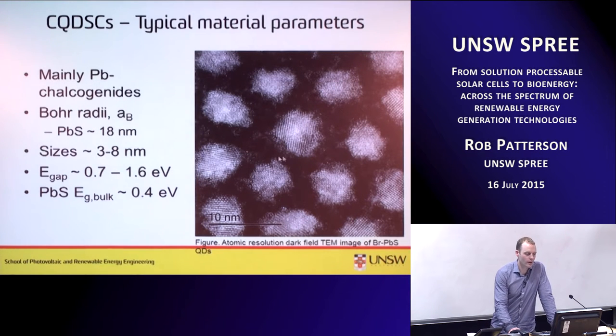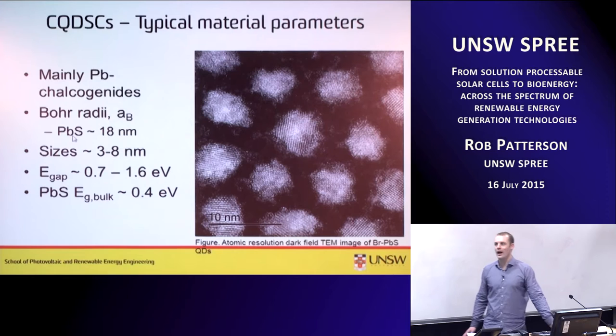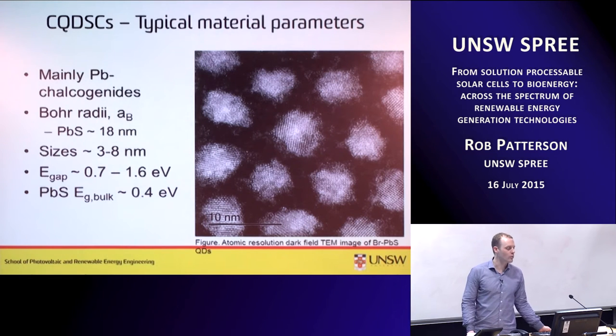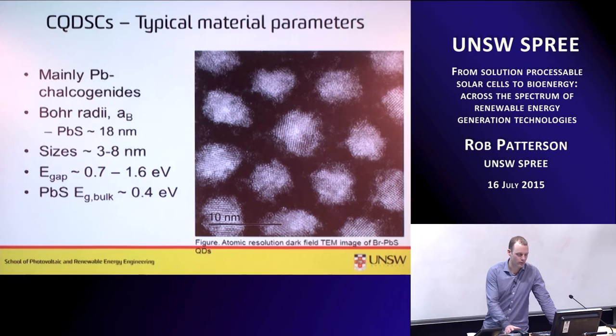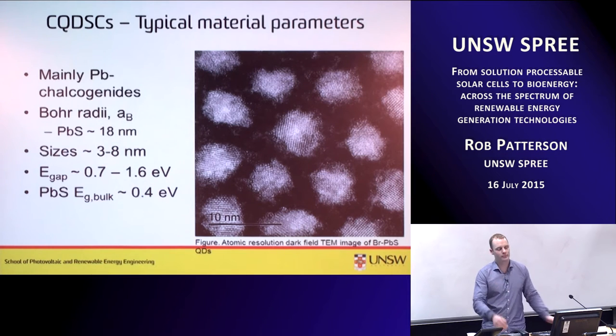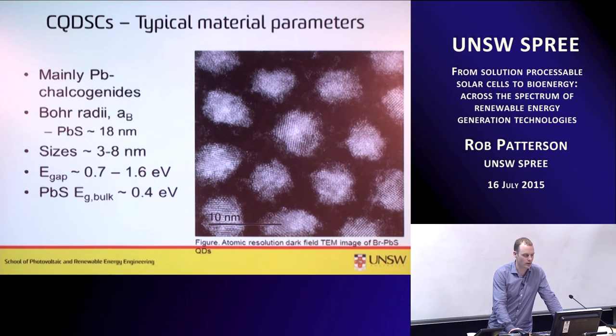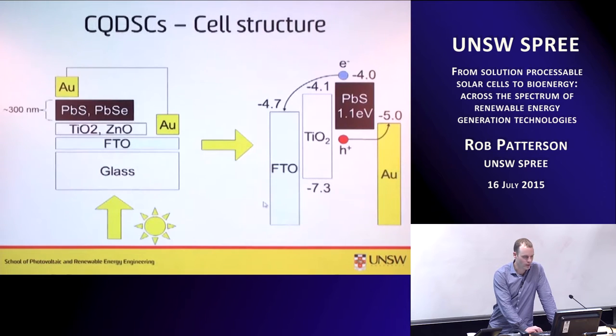So we like materials that have large atoms in them because they have potential for large Bohr radii and large confinement effects. So we can really expand the band gap using these materials with big atoms in them. And here's a dark field TEM, taken at University of Wollongong, made by Lin Yuan, who's here today with us, of bromine terminated lead sulfide. This is a wonderful TEM shot. I think it's so beautiful, I had to show it to you. Look at the fringes. You can really see the atoms in this. That's a really nice shot.